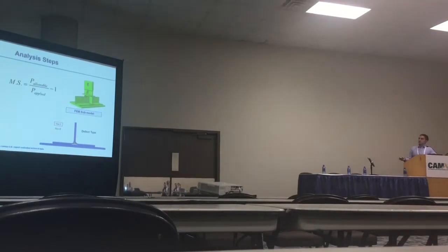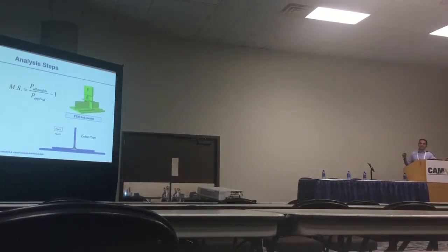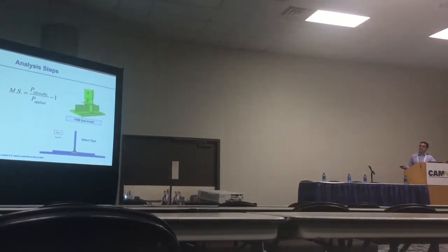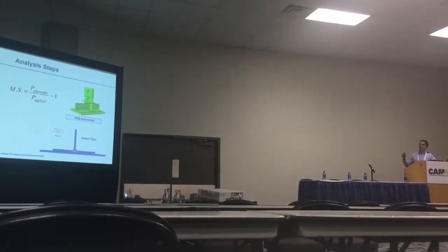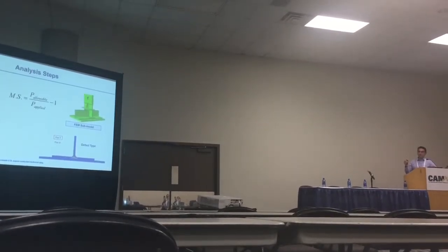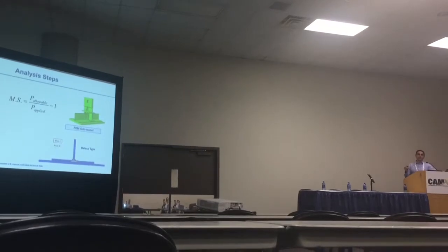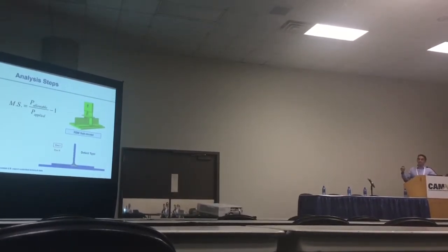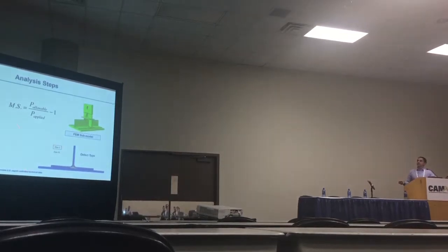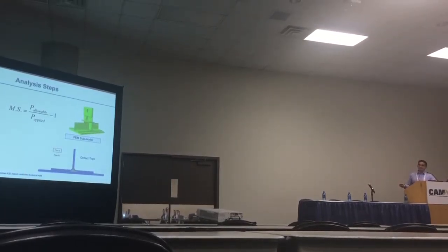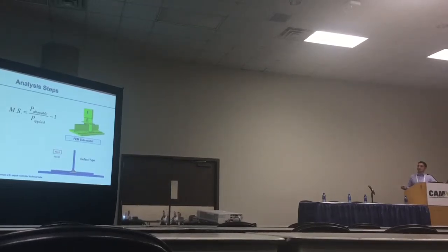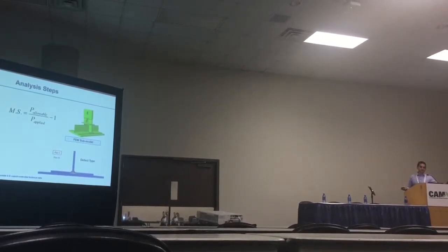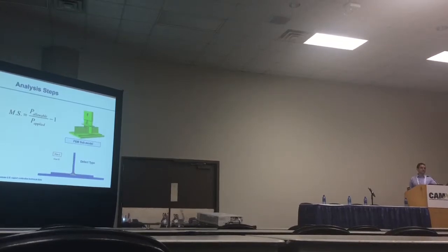Just to complete this, what you're seeing here are the steps of the model. I run a cool down from 350 to 70. The reason is that I want to understand the impact of the cool down, because it has a substantial impact on the cracking. Then I also include fastener preload, which doesn't have a substantial effect but is included for accuracy. And finally, the actual mechanical load, which in this case is a pull-off.